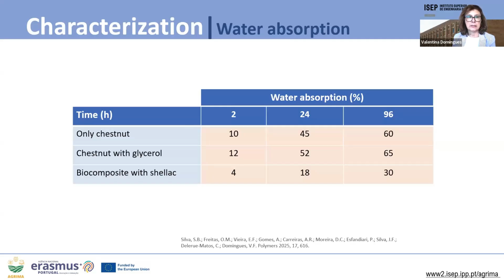Water absorption tests reveal that biocomposites without glycerol, only chestnut, absorb 10% of water after 2 hours, increasing to 45% after 24 hours, reaching about 60% at 96 hours, due to the hydrophilic nature of starch and fibers.